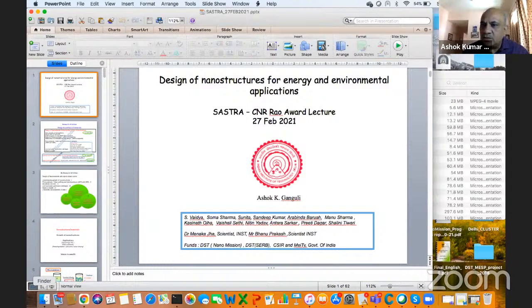So all the physicists who used to work on simple metals, say silicon with something, these are of course a little more complex because chemists work with more complex things. But even in simple materials, where you have two alloys, interdiffusion is a very important thing, and one has to control that. If you cannot control that, then what you are trying to do, make those two semiconductors be segregated, will not happen, and then you will not get the designed effective band gap and the band bending. So that interdiffusion has to be stopped.